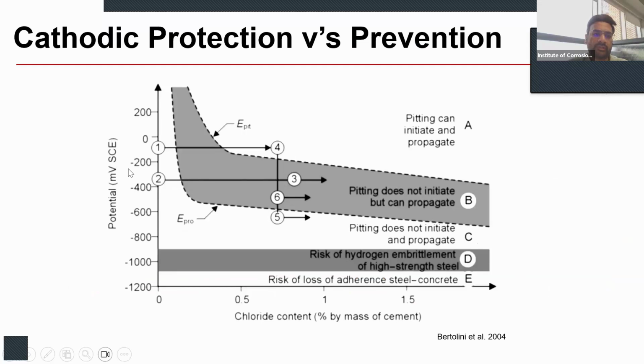If we look at the difference between cathodic protection and prevention, the potential of steel lies somewhere around less than minus 200 millivolts versus SCE when it's not corroded. That means it's in the zone where pitting does not initiate and propagate. When chloride content increases and corrosion initiates, the potential moves to a zone where pitting can both initiate and propagate.